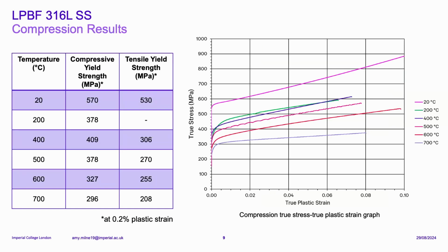So these are results from the compression tests, and you can see that, as expected, the compressive strength decreases as temperature increases. The compressive yield strengths are also much higher than all of the tensile yield strengths, with the exception of 200, which didn't have a tensile yield strength result. And these were all taken at 0.2% plastic strain.